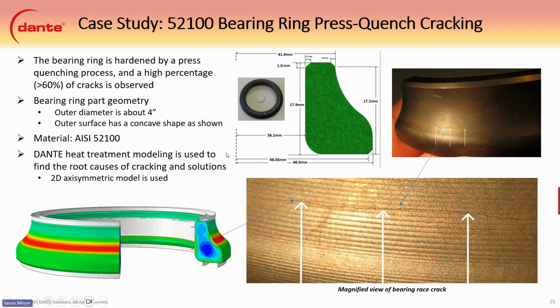All right, our last case study here has to do with the 52100 bearing ring. This ring is hardened by a press-quench process, and a high percentage, about 60% of them, are cracking. There's the ring geometry, and it's about a 4-inch ring here. And the outer surface has this little concave shape, as you see here, for the bearings to ride on.